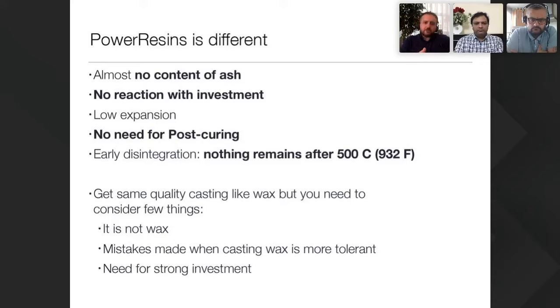You have a very low expansion, and one important thing when you print is you don't need any post-curing. Our resins are able to disintegrate quite early in time, and after 500 Celsius, there is nothing that remains. I have some customers who try to go up to 800 Celsius or more, thinking that if they go to 800, 820 Celsius during the process, they will remove the whole resin. But actually you don't need that, at least with our resin, because after 500 degrees everything is finished for the resin side.